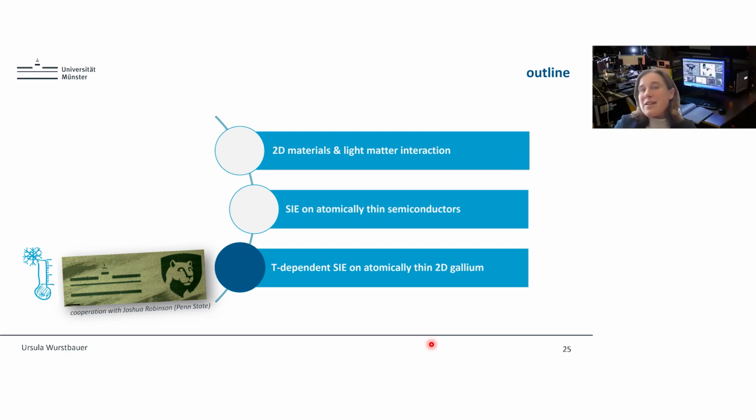So those are the arguments for certain substrate materials. Then the thickness. Well, in our experience, AFM is, for these two-dimensional materials, not that accurate as, for instance, ellipsometry and also Raman, because we measure all dirt, all stuff, if you're not going to ultra-high vacuum. It's well known that if you do it in ambient, we always have some water layer on the surface, which is, of course, then also present in this measurement.